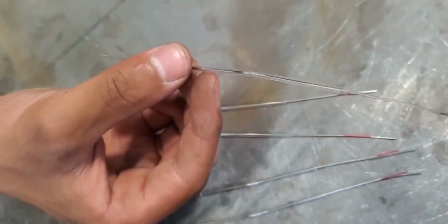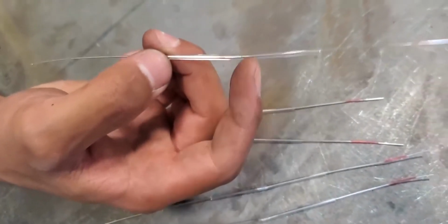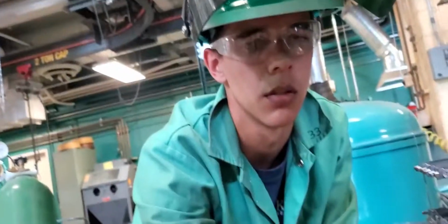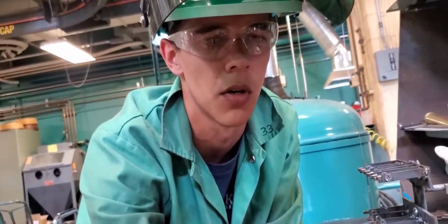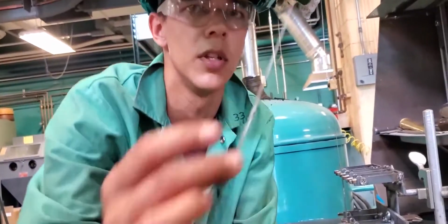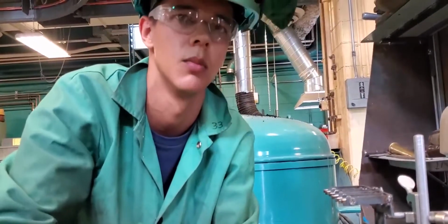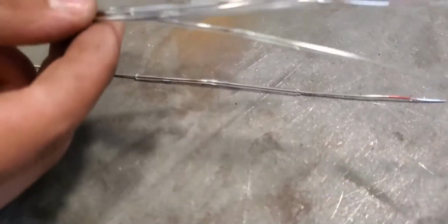See, they are a little bent. If you don't kind of like anneal them with the torch a little bit beforehand, all the residual stress from it not being so straight kind of bends the quartz as it gets soft with the torch. So doing a little bit of an anneal pass really helps with that. That one's good too. So 100% success rate there.